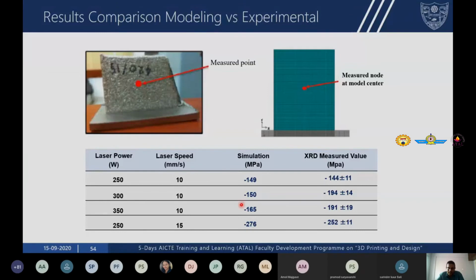results are obtained. You can clearly see the simulation results and X-ray diffraction values of residual stress for different process parameters. You can see that there is a good agreement between the simulation and experimentally measured results in terms of the distribution, that is the sign of residual stress, as well as the magnitude.